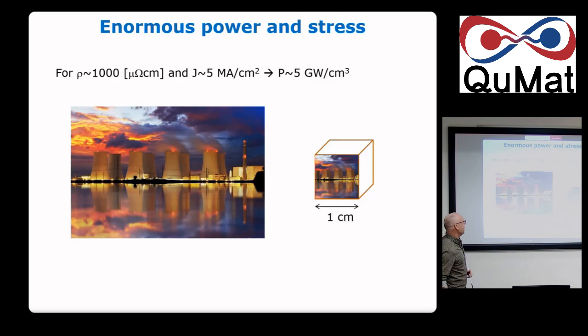But okay, this is a very high current, and the example I'm going to give you here is one of the materials I will show you at the end. I just plug in the resistivity of the material and the current density we need to move atoms. I make the product, and my power density is about 5 gigawatts per cubic centimeter. This is about the power of the nuclear plant we have in Belgium in 1 centimeter. So it's a huge amount of stress you put on the sample. More or less it's the same energy you need to ablate the material with a laser. So it has to be something of that scale.